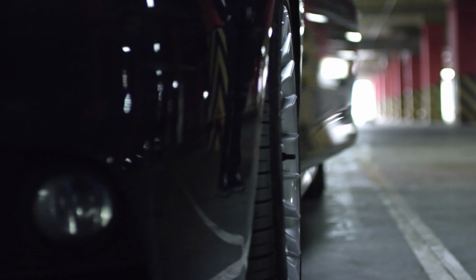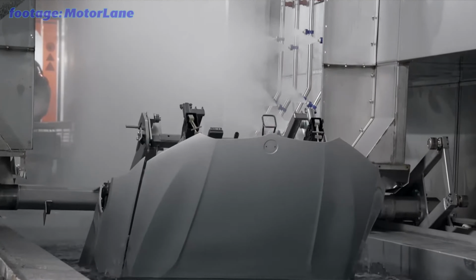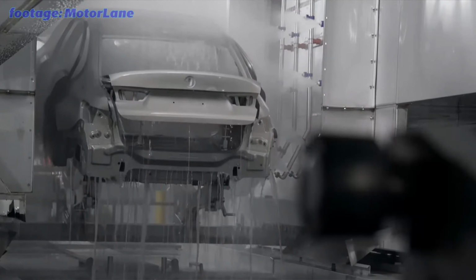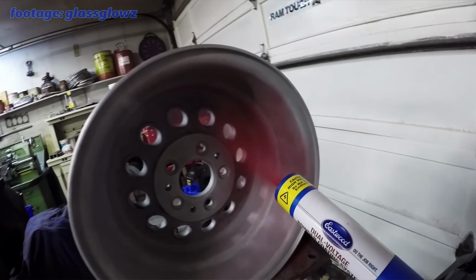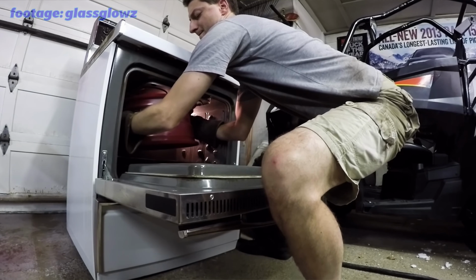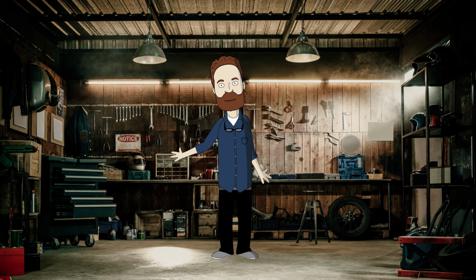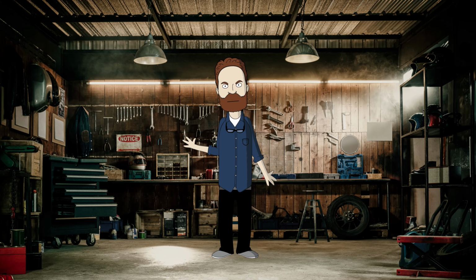Powder coating on wheels may look the same as your car paint, however, it's a completely different paint type. Your main body paint is applied by robots in special paint tubs in several layers and then dried. Powder paint is applied dry and looks matte. Then it's placed into a special oven and baked at 390 Fahrenheit or 200 Celsius. Powder paint will cure only at high temperatures, which makes it more durable and, at the same time, suitable for